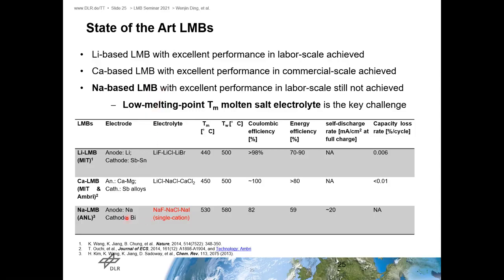Some reviews say maybe the molten salt electrolyte is the key challenge, because it needs to have a low melting temperature and also good electrochemical properties. As shown here, these two have good battery performance, but the sodium liquid metal battery uses sodium salt mixtures, and the melting temperature cannot be below 500 degrees C, and the working temperature is about 600 degrees C. At such high temperatures, the sodium metal solubility becomes a problem, then the self-discharge rate will be higher, and there are also many problems like corrosion.